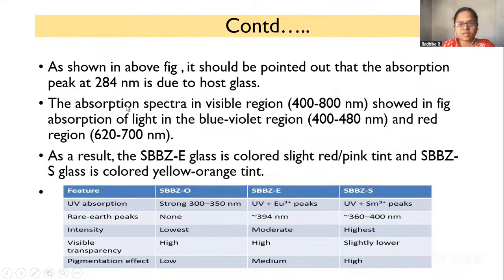The absorption spectra in the visible region is near 400 to 800 nanometers. The absorption of light is in the blue-violet region and the red region, 620 to 700 nanometer. As a result, rare earth doped glasses are colored: slight red or pink for europium, yellow-orange tint for samarium. And this is the observation analysis that can be observed here.